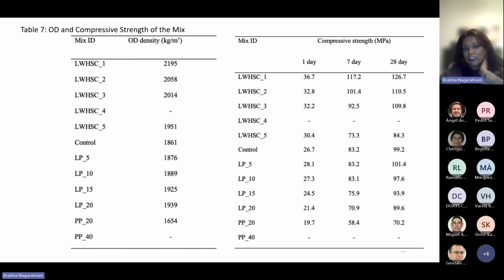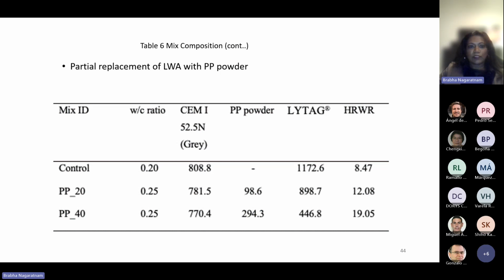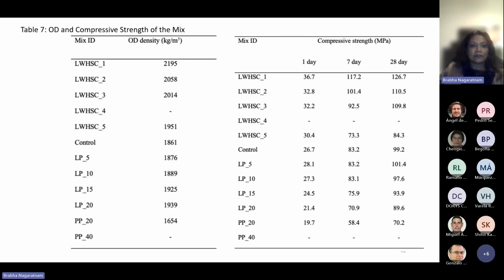You can see we have achieved some above 100 MPa, 120, 100. So this is possible to achieve: lightweight, high strength, high performance concrete, above 100 MPa. And one of the things that I want to highlight is we did not use any of the normal silica fume additives. We use everything locally for the local construction companies. That's all the mix designs.